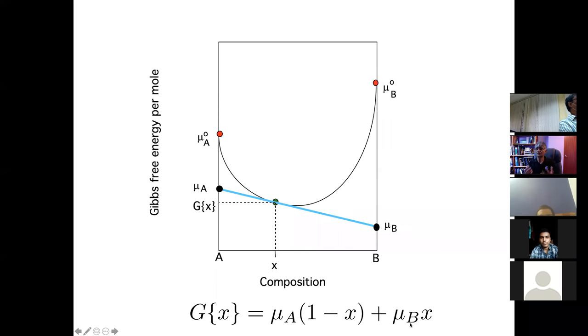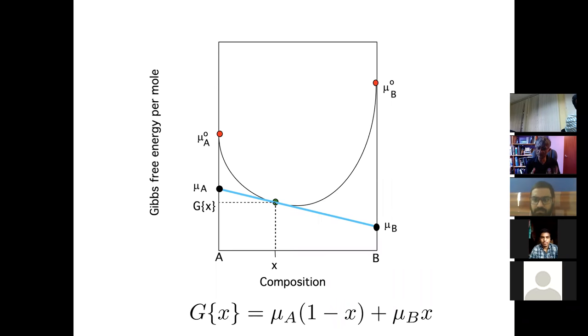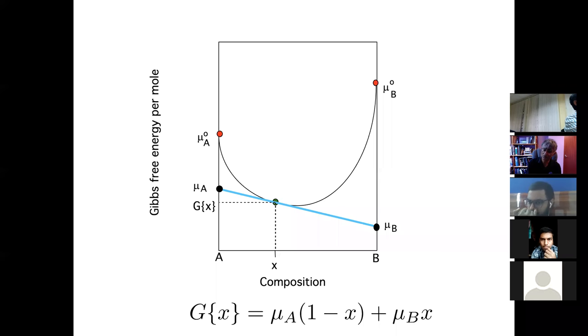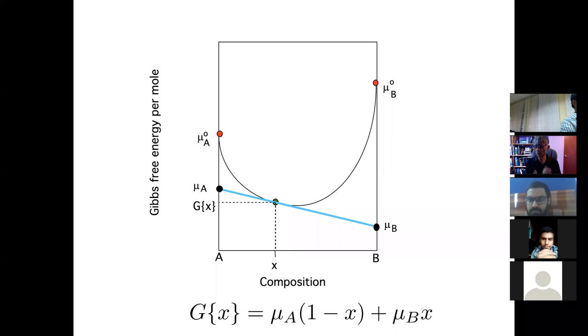The chemical potential is simply the average free energy of an A atom in a solution of a particular composition per mole of that solution. Similarly, the chemical potential of B is simply the free energy of a B atom in a solution of that composition. So the physical meaning of chemical potential is that μ_A and μ_B define the contributions of those particular elements to the free energy of that solution. These chemical potentials are a function of the composition x.